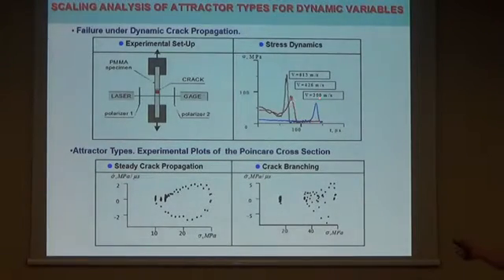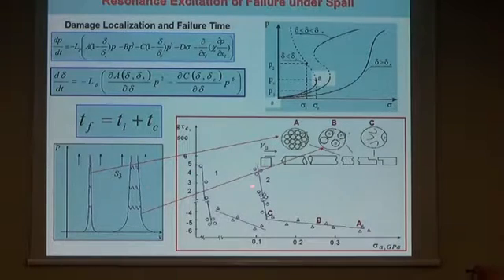You can see that when the crack begins to branch, we have these finite amplitude disturbances for stress. And when we plot the phase portrait, steady crack propagation corresponds exactly to hyperbolicity. But when we have branching, you have a strange attractor that is exactly related to the set of collective modes responsible for damage localization in the blow-up region. And there is exact correspondence of this scenario of crack branching with this pattern of numerous spall failure with generation of numerous mirror zones along the dynamic branch.